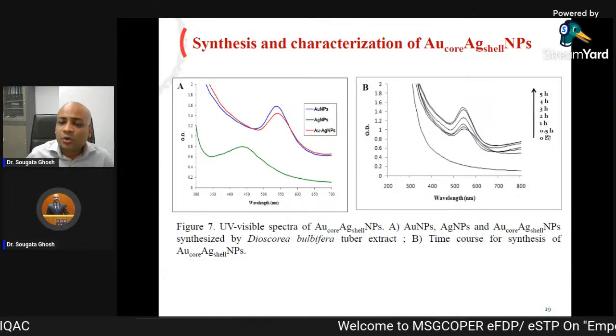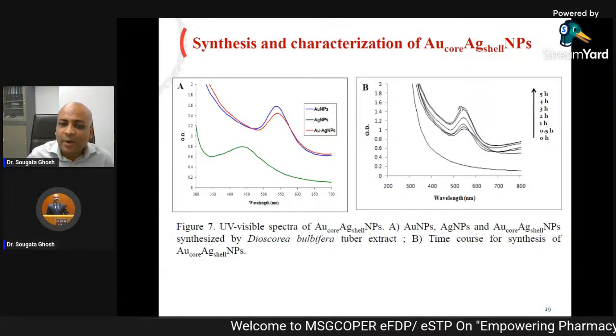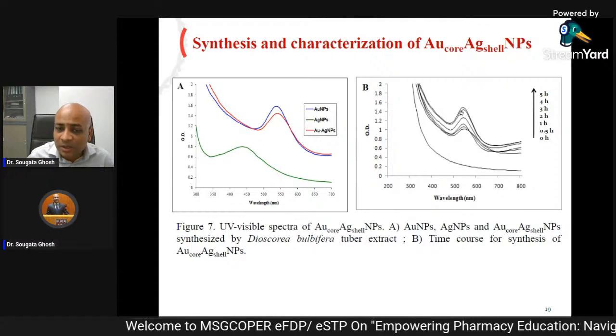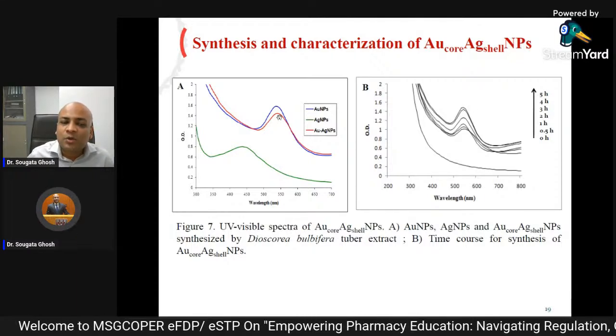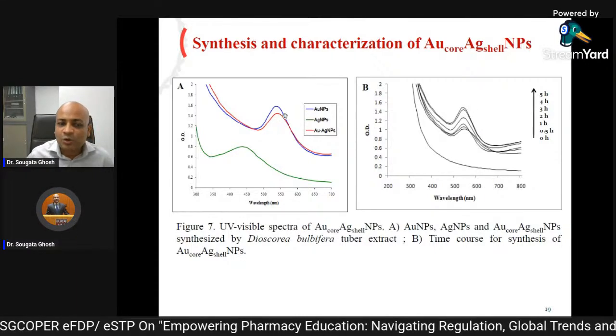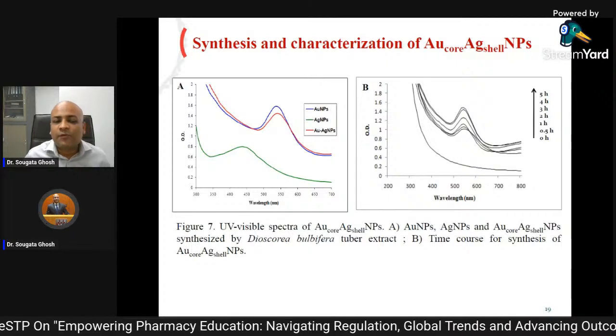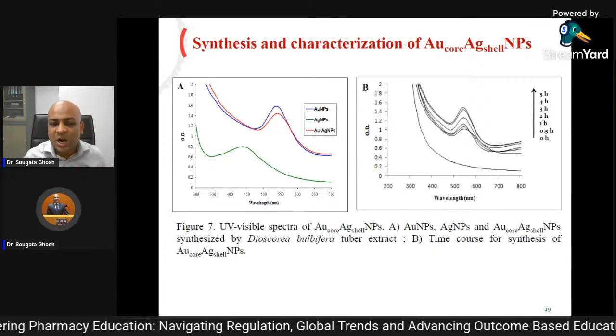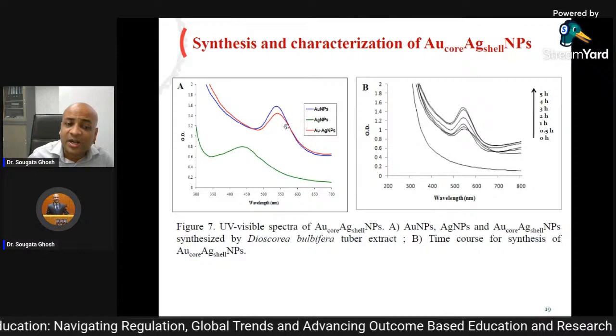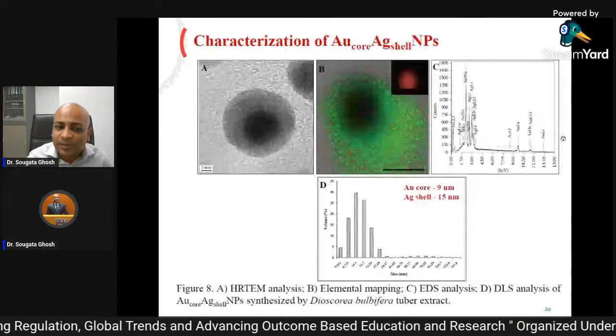And we synthesized for 5 hours, and at 5 hours the synthesis was complete. So at this point, we knew that when we combine silver and gold, it is not a mixture of only silver nanoparticle and only gold nanoparticle. It's not like that. Something different is getting formed. So what is this something?